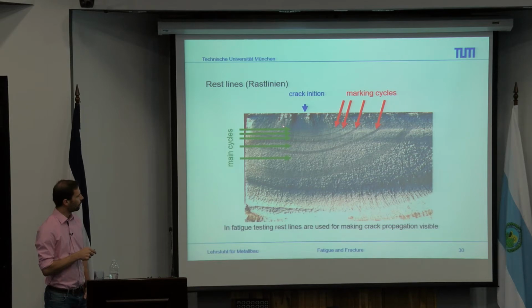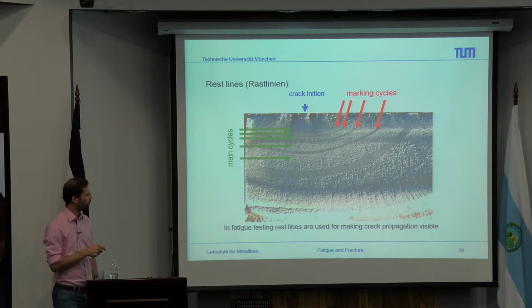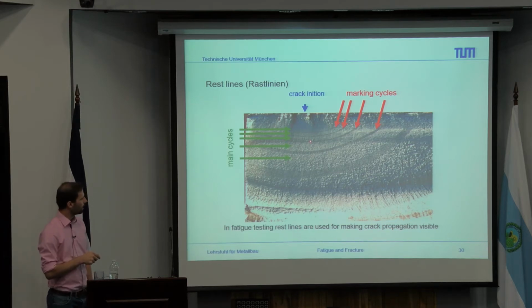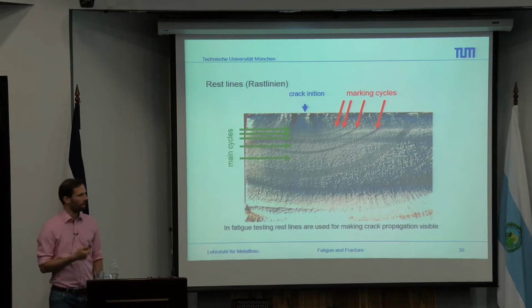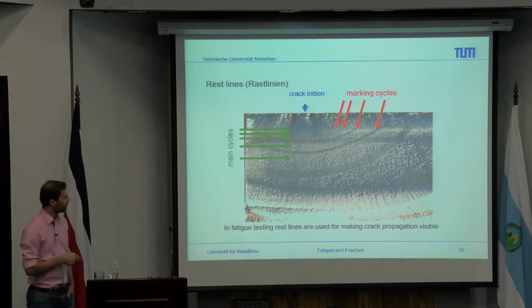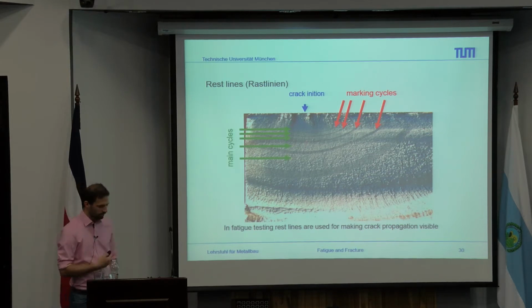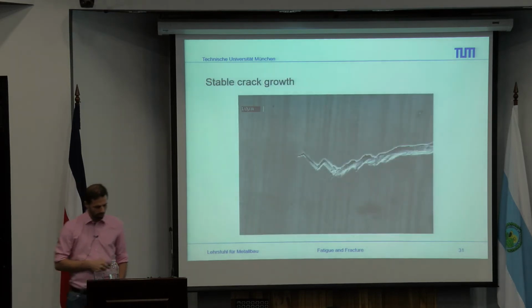But due to the curves, you can see that the crack initiation was somehow more on this side than on this side. And due to this, you also see the marking cycling, so the rest lines, and the main cycles, which are the crack propagation. And this is usually how it looks like, and then some stable crack growth.